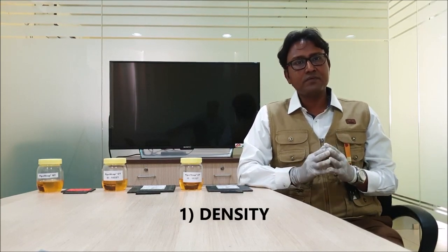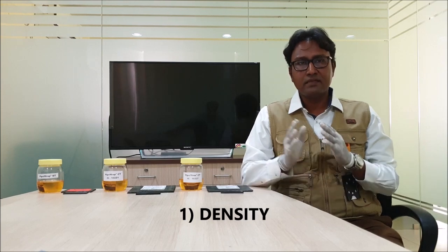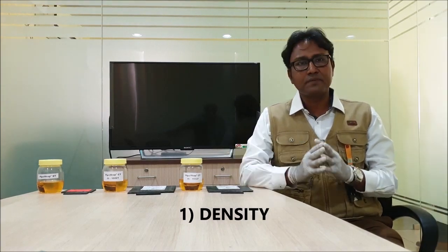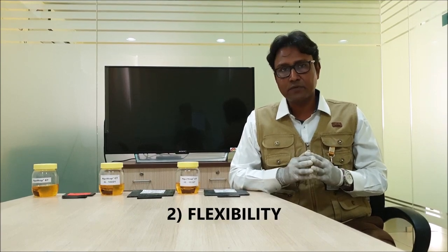The first point is the density. Every supplier promises a certain product density, and these are 4 mm tapes which typically come in 1 meter wide by 10 meter long rolls. And there is a product density which is mentioned. When we weigh any roll as a part of our quality check, it should fall within the promised standards with its given deviations. This is the first check to ensure that the product quality is in line with what has been promised. The second check is the flexibility of the product.